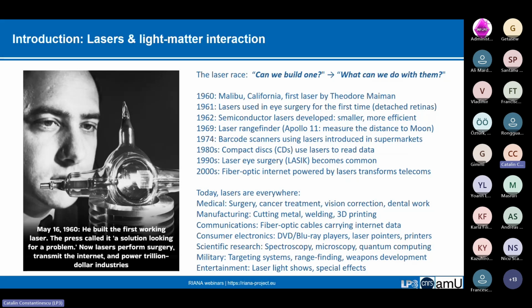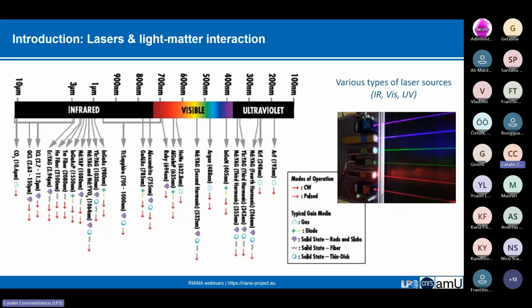This versatility also comes from the diversity of laser sources available today, and that's really important because if we consider lasers from infrared to ultraviolet, the wavelength selection allows us to tailor absorption mechanisms from phononic to electronic to nonlinear, depending on the material and the targeted processes. For example, in our case here at LP3, most of the experiments that we do use ytterbium YAG, yttrium aluminum garnet, that works at 1030 nanometers. We can also use the higher harmonics, and also neodymium YAG as well.